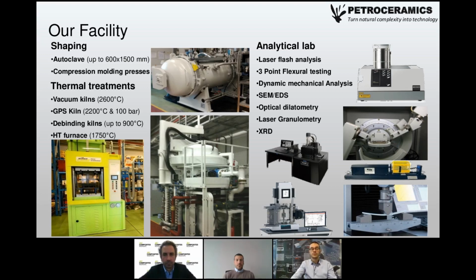We can work up to 2600 Celsius degrees in vacuum. We can work up to 2200 degrees in 100 bar of inert gases, and up to 1750 Celsius degrees in air. And in our analytical lab, we can characterize the materials from the point of view of mechanical properties, thermal properties, physical textures, and a lot more, as you can see from the images.